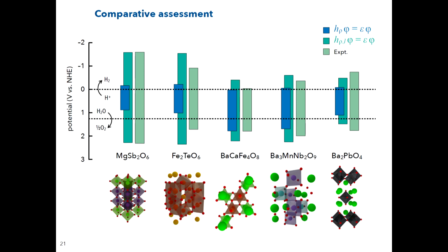And you can see that in most of the cases we get good agreement, or we tend to overestimate the band edge position, so that you can get essentially a window of upper and lower bound if you use the vanilla DFT and this angular momentum resolved DFT. And so based on this, you can have a solid basis to do your screening.